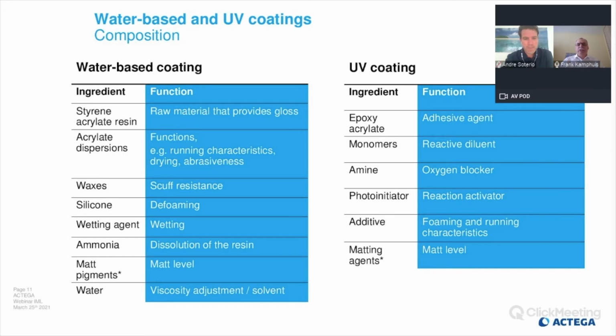In principle, there are two technologies in the market, UV coatings and water-based coatings. Starting with the UV coating, it is based on epoxy acrylates, monomers, and contains some photoinitiator and additives. To dry this UV coating, you need UV light, and then you get a chemical reaction. Water-based coating has polymers based on acrylate, styrene acrylates, some waxes, silicones and wetting agent. But more importantly, you have a solvent, and the solvent for a water-based coating is water. That is very important, that we are not using any other solvents like alcohol or glycol ether.